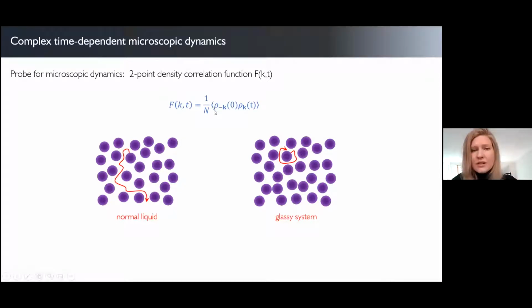And in particular, in the Fourier domain, this function can be defined as a correlation function between two density modes, one at time 0 and one at time t, for any given wave vector k. And k then basically sets the inverse length scale over which you want to probe the microscopic dynamics for that particular length scale. So simply put, this dynamic correlation function tells you essentially how rapidly particles lose track of their initial positions.